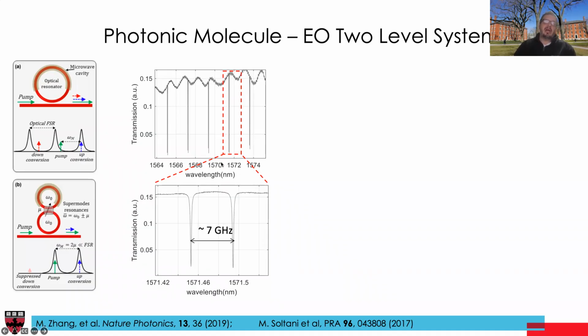But basically, what happens is you form this doublet, and you can think about this as a coupled quantum well. And what's really interesting in our case is that in analogy to a coupled quantum well, where if I have 2 levels for an electron, I can apply an optical signal to make a transition from one level to another. In our photonic molecule, I have 2 optical levels, 2 optical modes, and I can apply an RF signal to drive a transition from one mode to another. That is, to drive light from this resonance to this resonance and back.